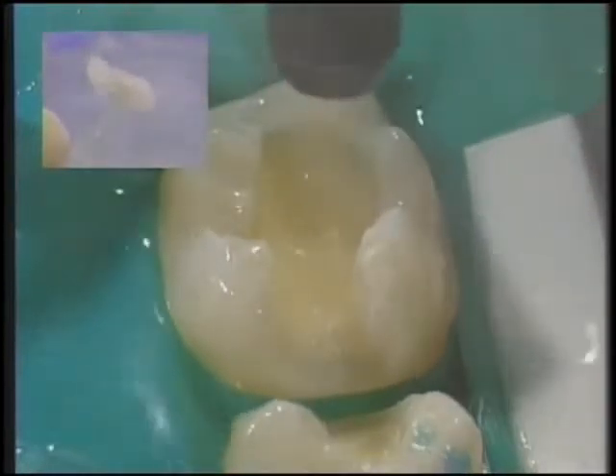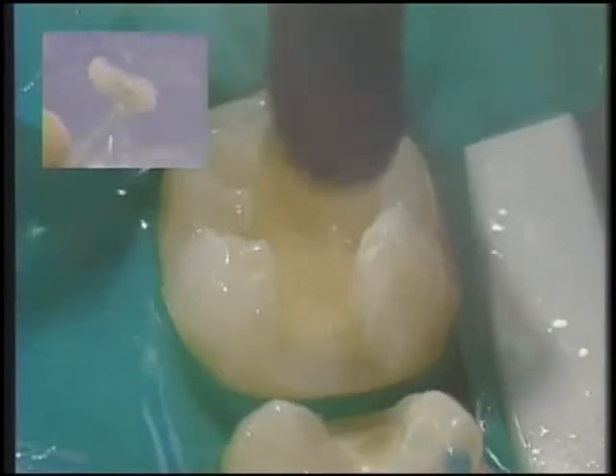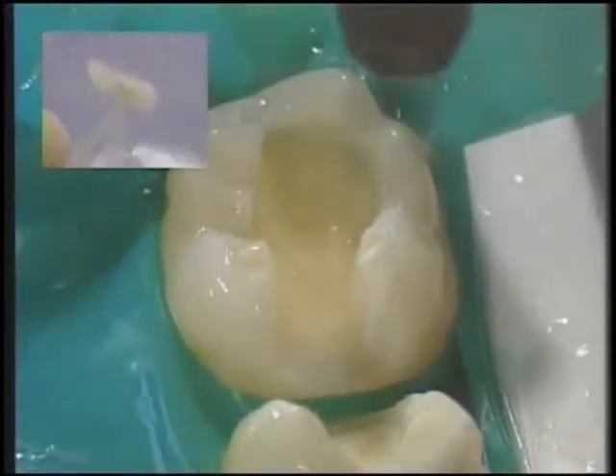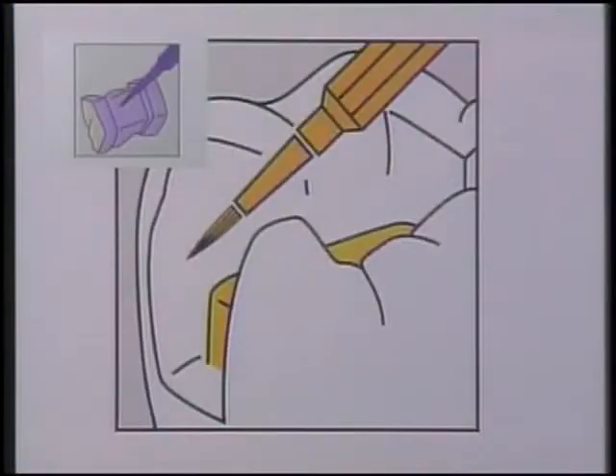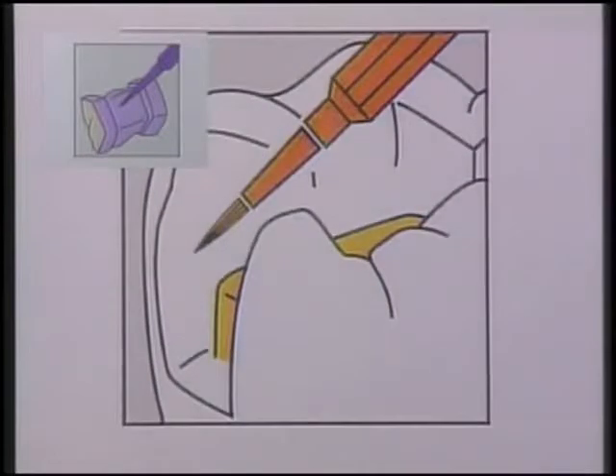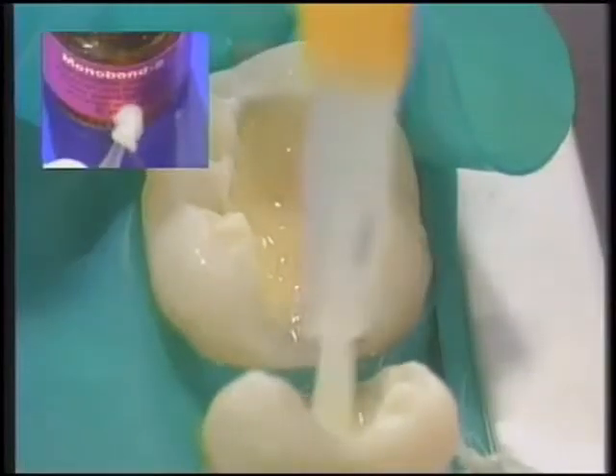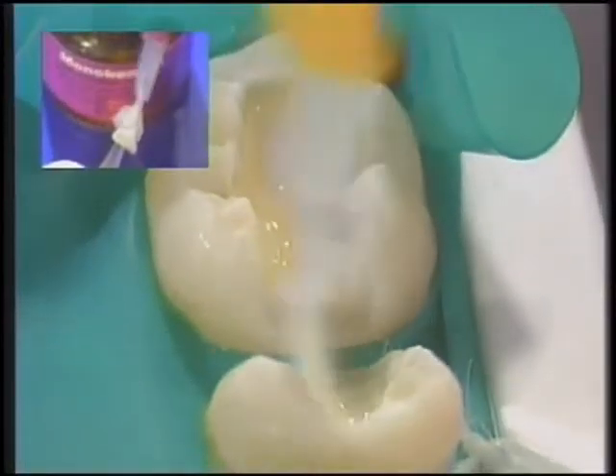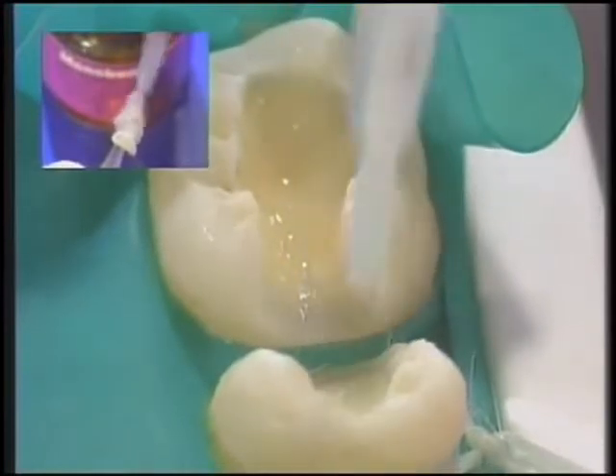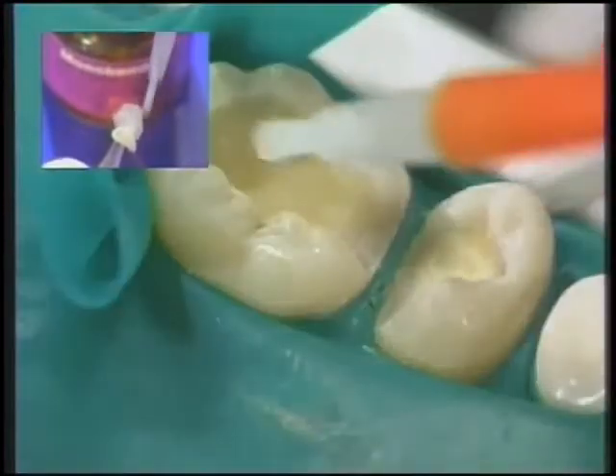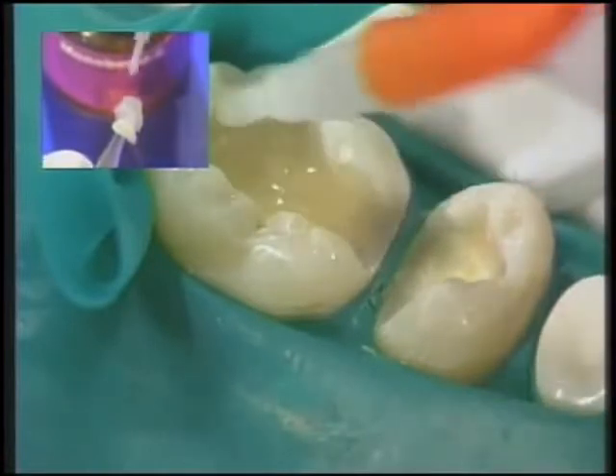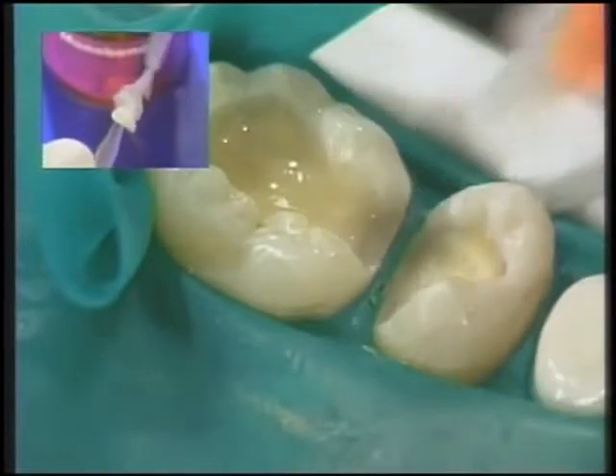The rinsing medium containing hydrofluoric acid should be neutralized before disposal. Please observe the safety measures. Syntac primer is applied to the preparation for at least 15 seconds and then dried. Syntac adhesive is applied in the same manner for 10 seconds. Then Monobond S is brushed on the inner surface of the ceramic for 60 seconds.